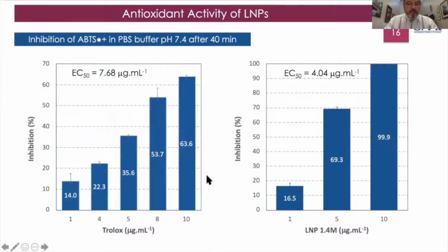Once again, talking about the calibration curve of Trolox, we could, by considering the data, calculate the EC50 values of Trolox. And this corresponded to 7.68 micrograms per mL. Whereas for the lignin nanoparticles, the same value, EC50, was only 4.04 micrograms per mL, showing already that those lignin nanoparticles were superior compared to the Trolox antioxidant.